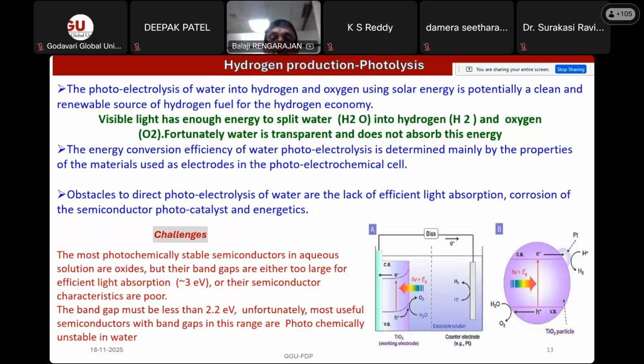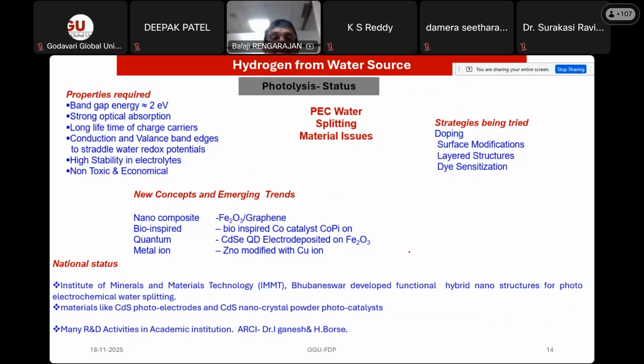There is some fine tuning of the electronic properties: you have to increase the electronic conductivity and reduce the resistance. In order to increase the electronic conductivity of the material, some dopant materials are added along with titanium dioxide to get the maximum conductivity, and it should be stable. Because of this, these photolysis routes are not taking place at a technological level, only at the R&D level. Various institutions, internationally as well as in India, are working on identifying a proper photoelectrocatalytic material for performing these photolysis reactions.